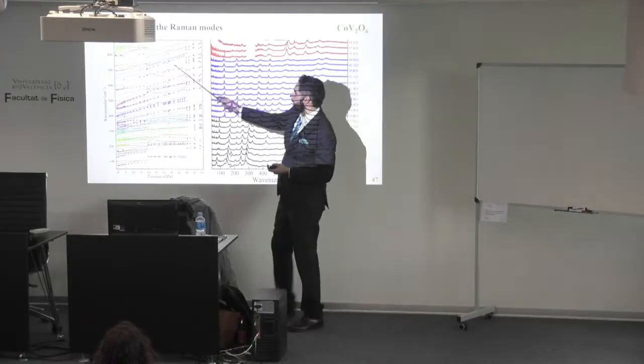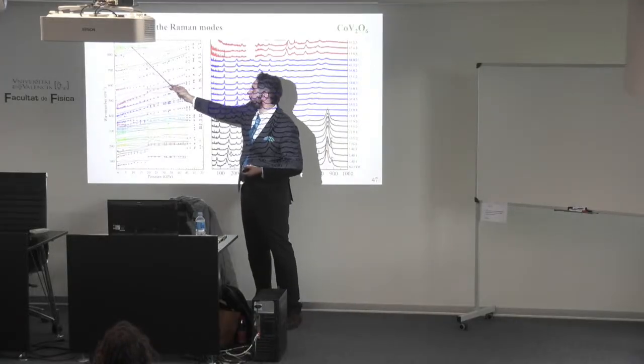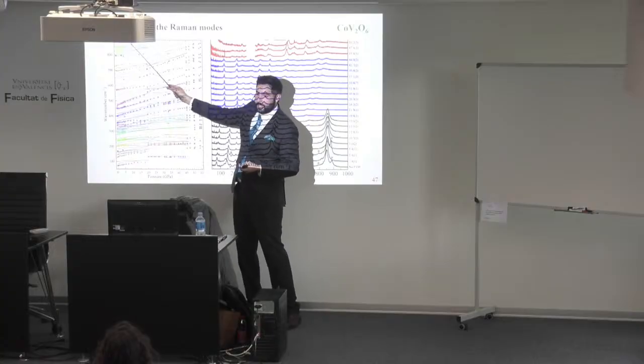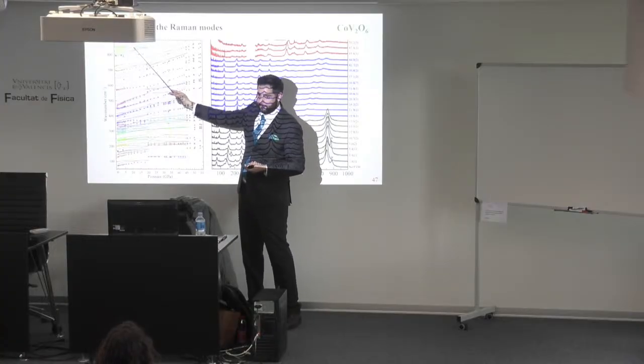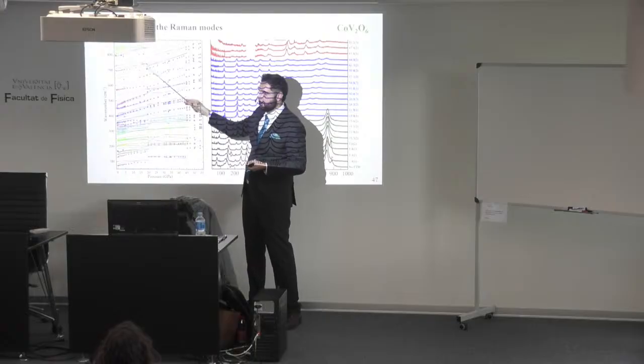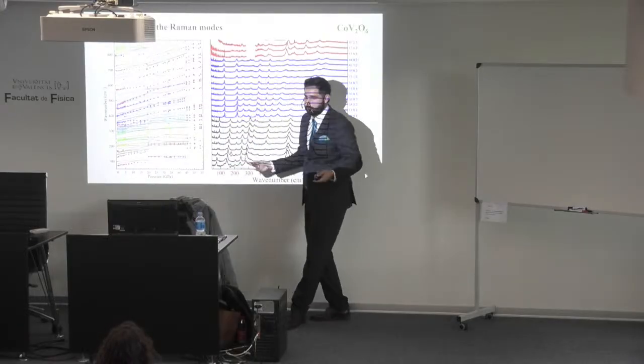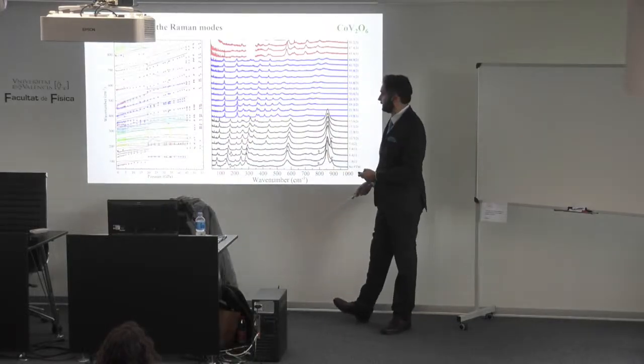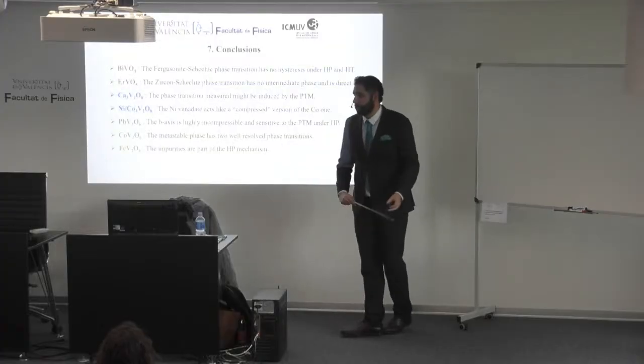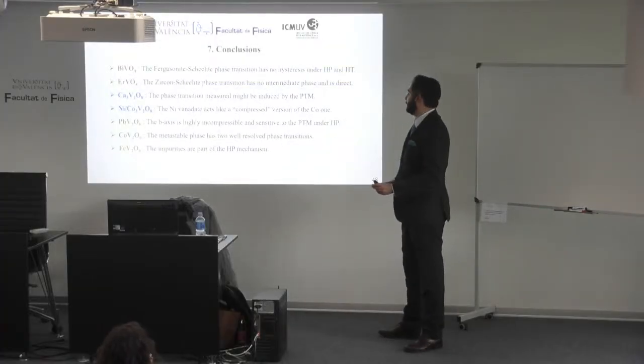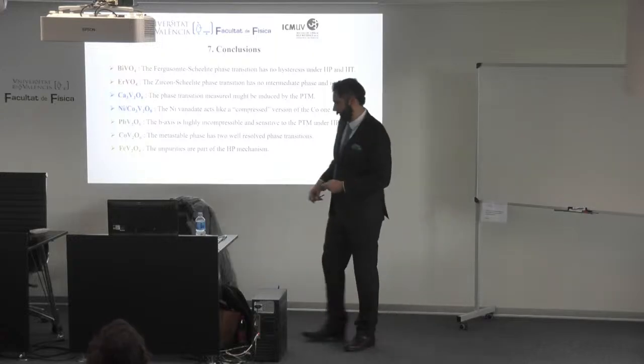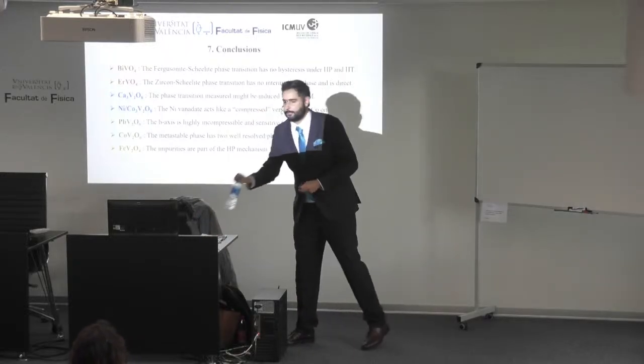Well, I can tell this one because it's the one that is softening and happens the same with the calculation and tells me a phase transition is going to happen. Well, but not the rest. So it was just tentative in this case. So this is the end of the discussion. We reached the conclusions. 45 minutes, so good time.